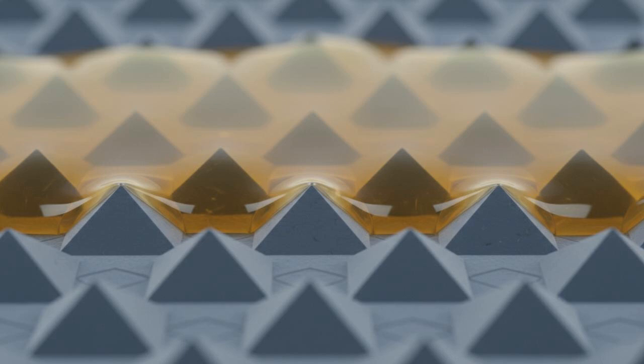One of the primary hurdles was the physical mating of the two materials. You see, modern silicon solar cells are not perfectly flat. Their surfaces are etched with microscopic pyramids. This texturization acts as an optical trap, forcing photons to bounce back and forth between the microscopic peaks and valleys, which increases overall absorption. However, trying to spin coat or deposit an ultra-thin uniform layer of liquid perovskite over a spiky pyramidal mountain range of silicon is notoriously difficult. If the perovskite pools in the valleys and leaves the peaks exposed, the cell simply shorts out.